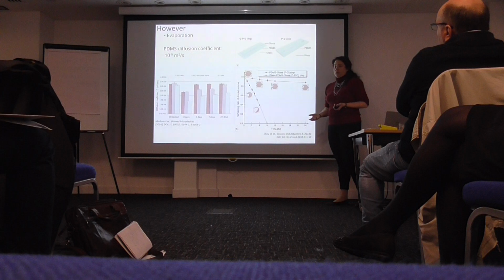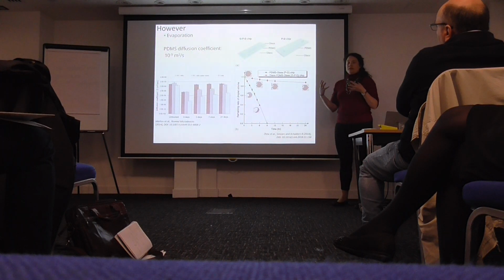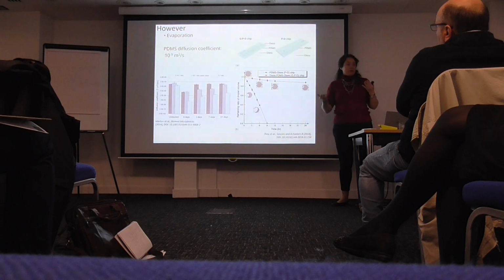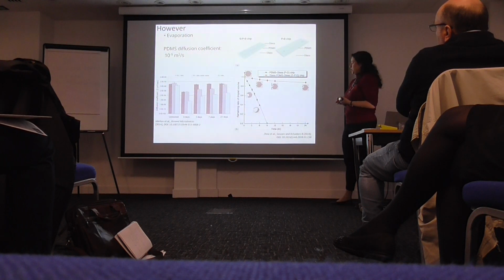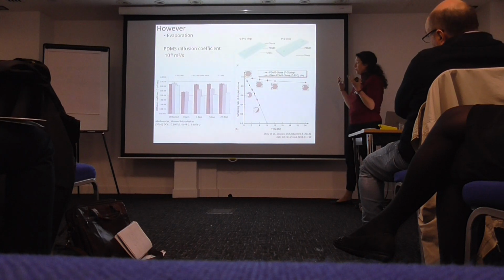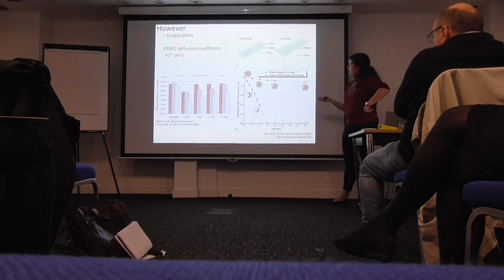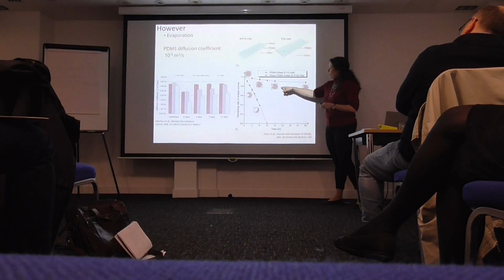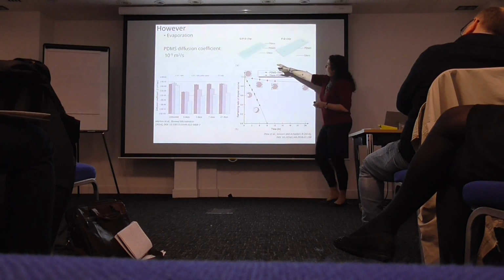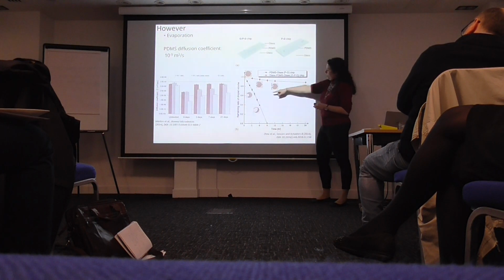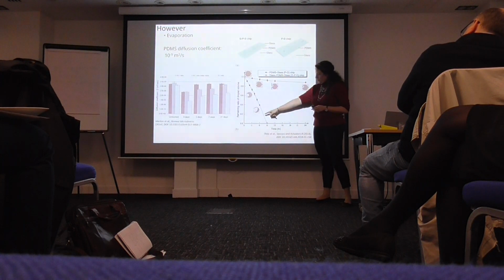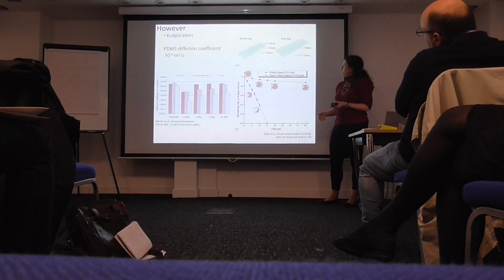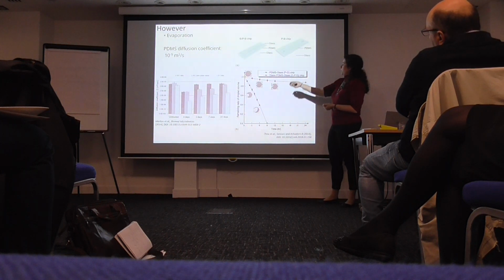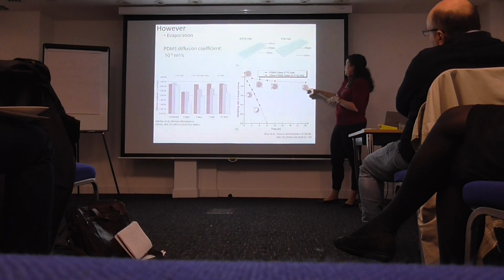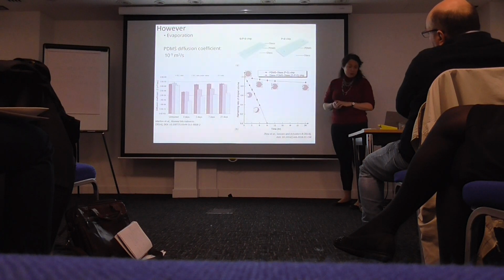You've got an evaporation problem with PDMS. PDMS is gas permeable, which is nice when you culture cells, because they're not going to need as much oxygen inside of the media, but because the gas goes through, you're going to get an evaporation problem. To prove their point, they created small reservoirs, and if you just do glass and PDMS on top, you're going to rapidly see, in a few hours, that you're evaporating most of your liquids. They showed that if you put glass on top of it, you're really reducing that evaporation process. So it's something that we need to take into account.